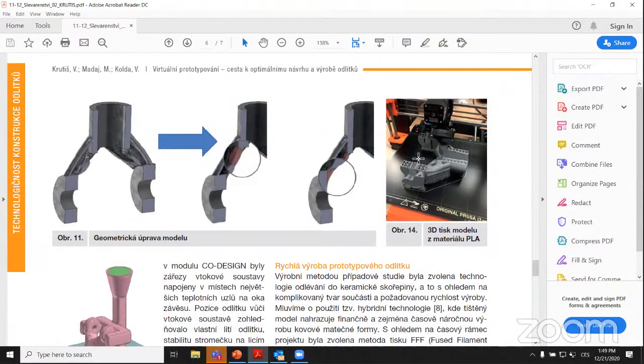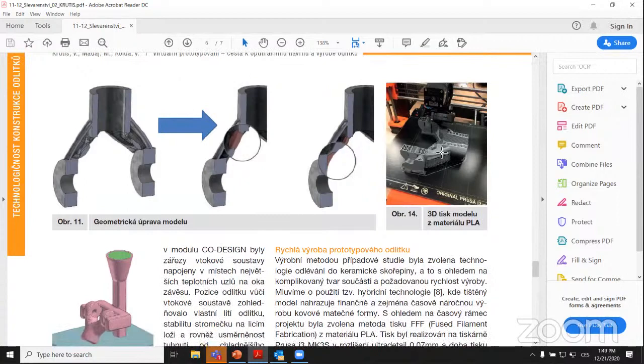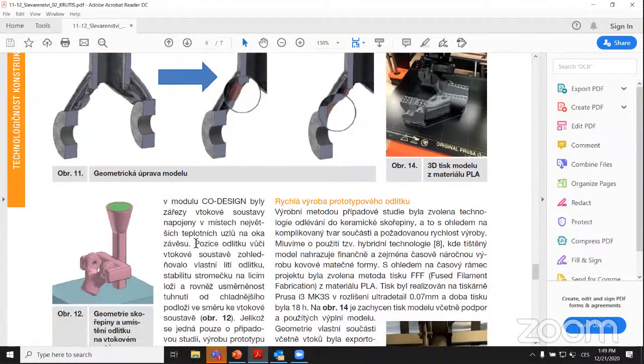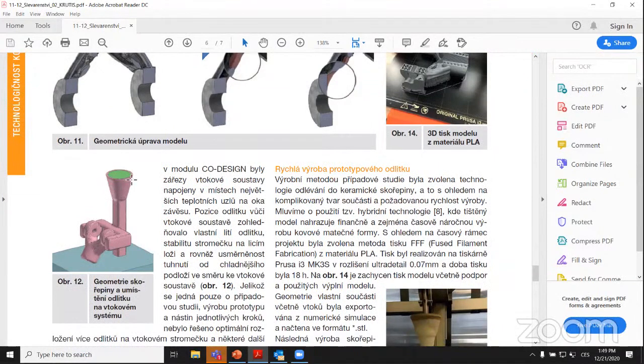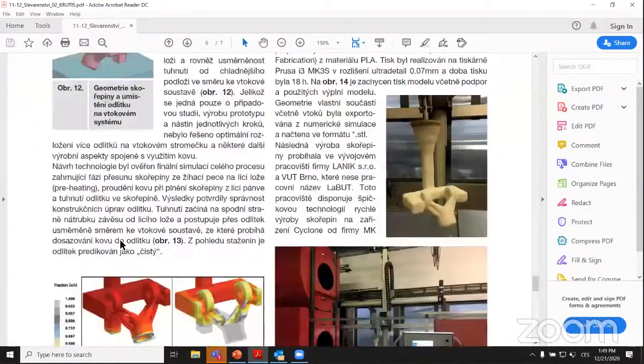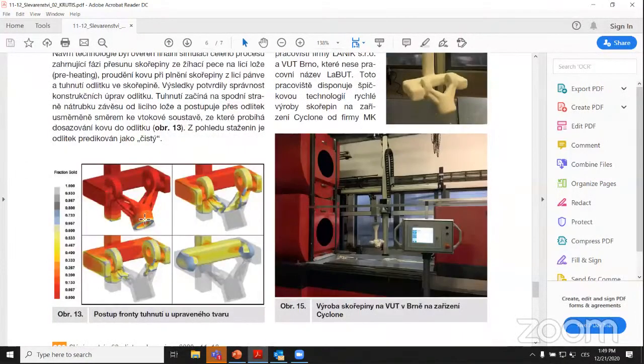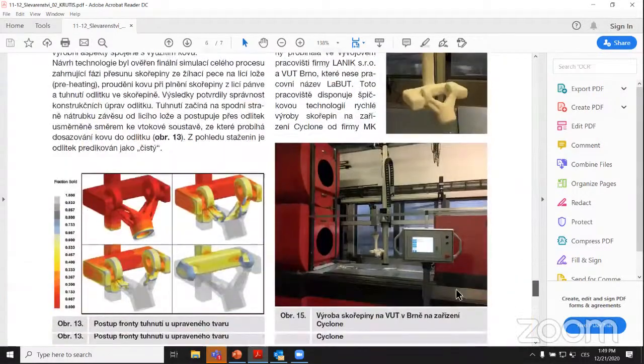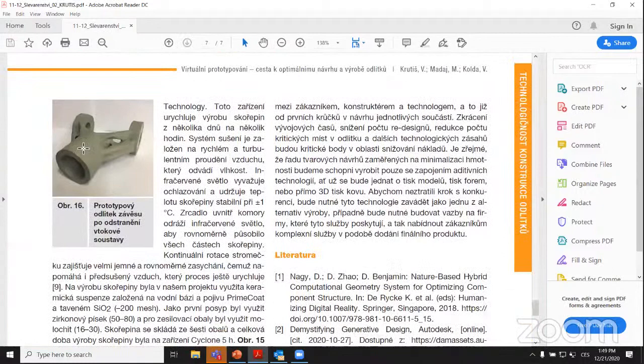We create the original model by additive manufacturing, printing the plastic model, which can then be used for the casting itself, because in this case it used the technology of investment casting, where you put the model into the ceramic shell. Based on the previous simulation, the second simulation was done, which already introduced some gating system, so the part was very clearly produced without any problem. And at the end, it was really done. The prototype was created and it was without any problem.